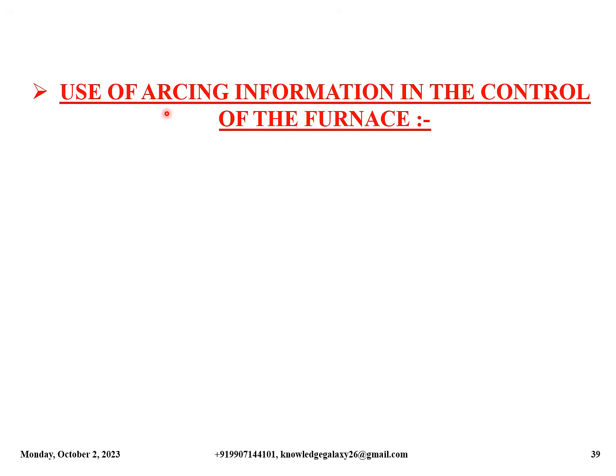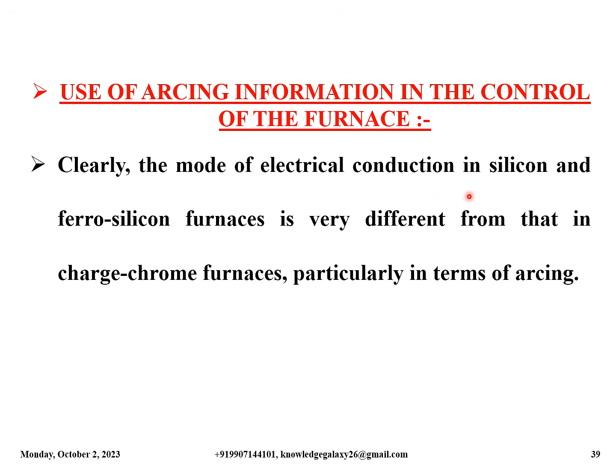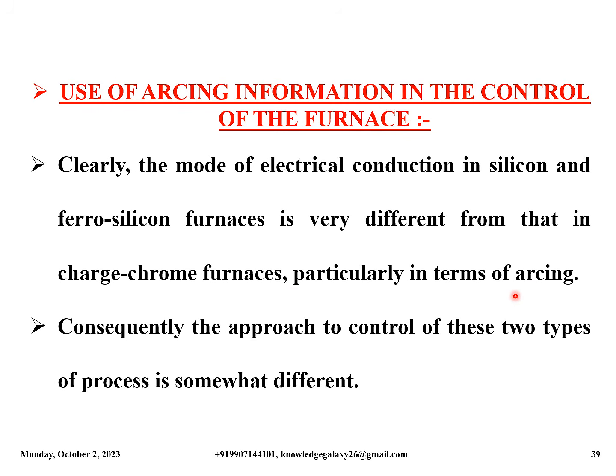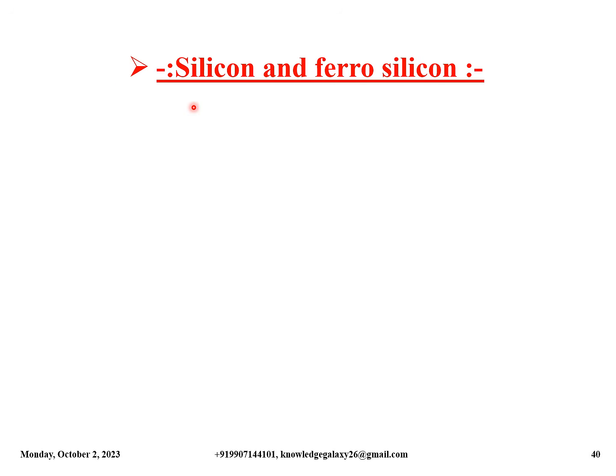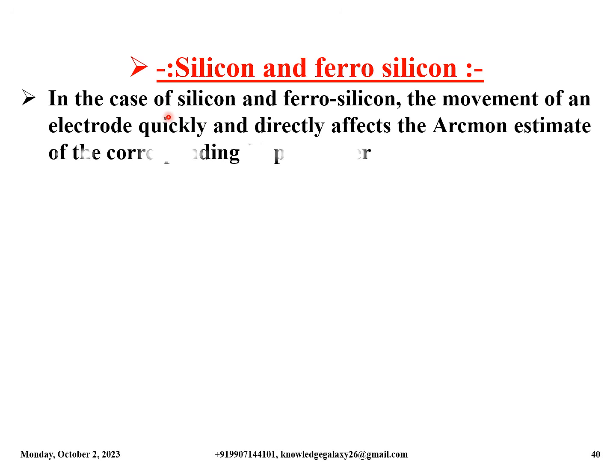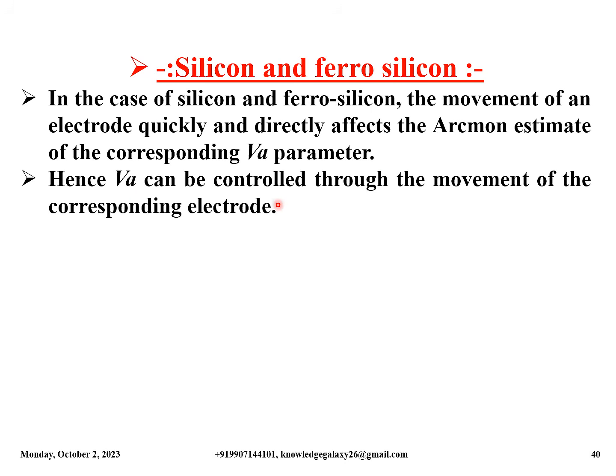So now let us discuss the use of arcing information in the control of the furnace. Clearly, the mode of electrical conduction in silicon and ferrosilicon furnaces is very different from that in charge chrome furnaces, particularly in terms of arcing. Consequently, the approach to control these two types of process is somewhat different. So now let us discuss these effects in silicon and ferrosilicon furnaces. In the case of silicon and ferrosilicon, the movement of an electrode quickly and directly affects the arcmon estimate of the corresponding VA parameter. Hence, VA can be controlled through the movement of the corresponding electrode.